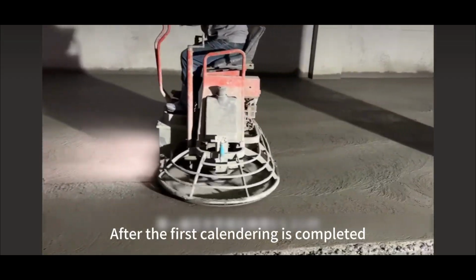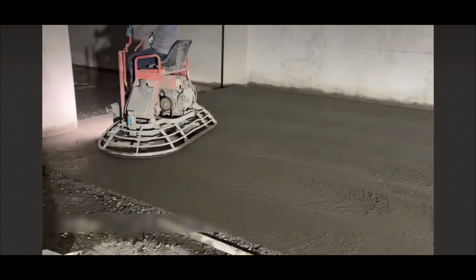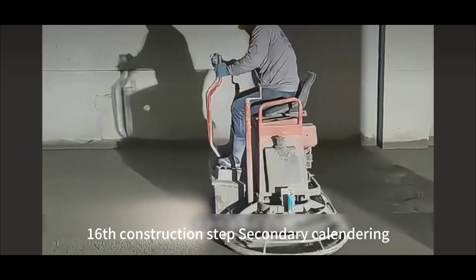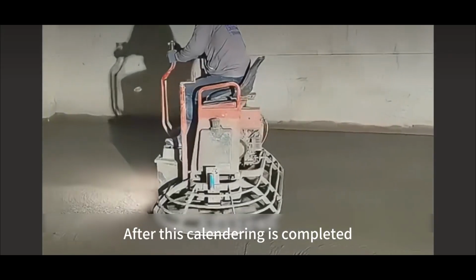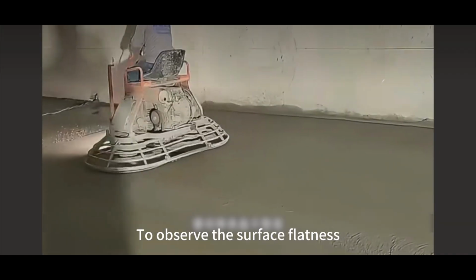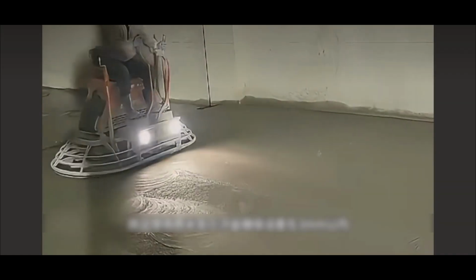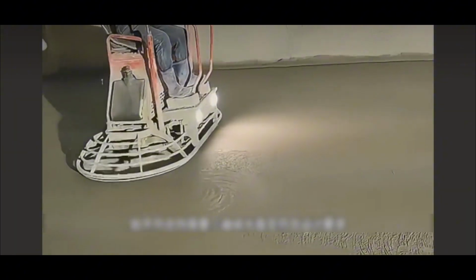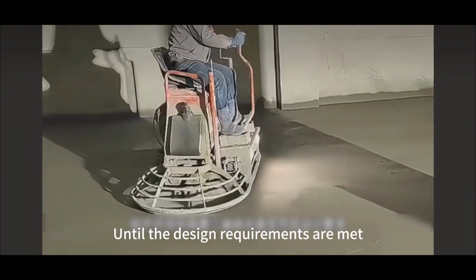After the first calendering is complete, let it stand for 0.5 to 2 hours. Sixteenth construction step, secondary calendering. After this calendering is completed, observe the surface flatness and measure with a 2-meter ruler. Make sure the error is within 3 millimeters. If it does not meet the requirement, you need to collect the surface 3 times until the design requirements are met.